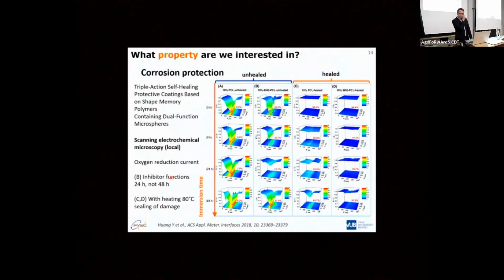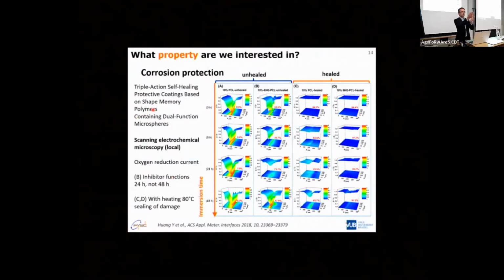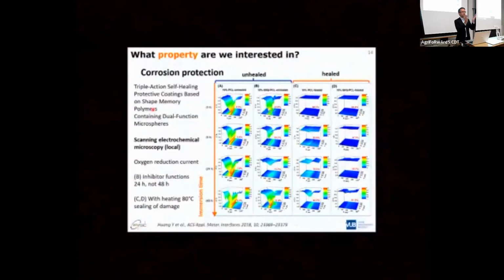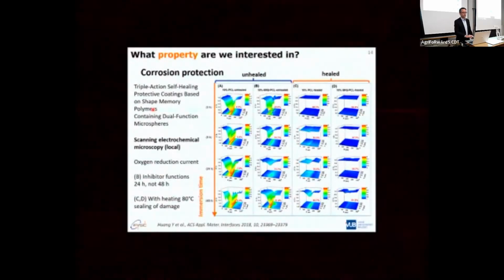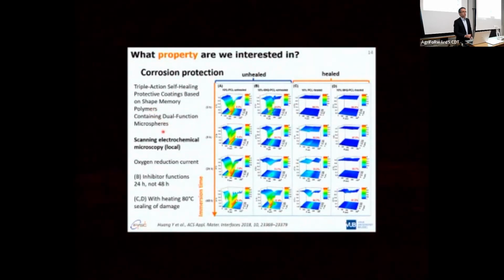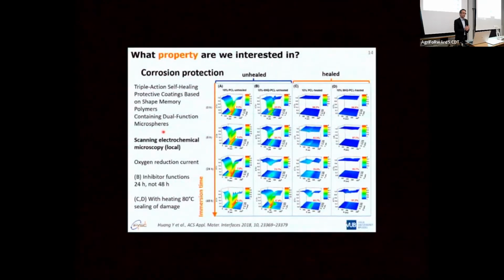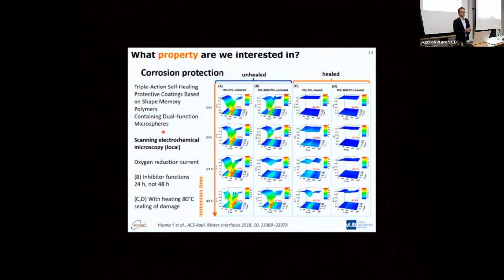We did some work on corrosion protection, although these are results from another group. They made a shape memory polymer, shape memory to be able to close a cut or a crack that you make into the material with a shape memory response. And they included microspheres with a healing agent to help this shape memory response, and with a corrosion inhibitor to make sure that, as long as that didn't happen yet, your metal that is underneath stays corrosion protected.